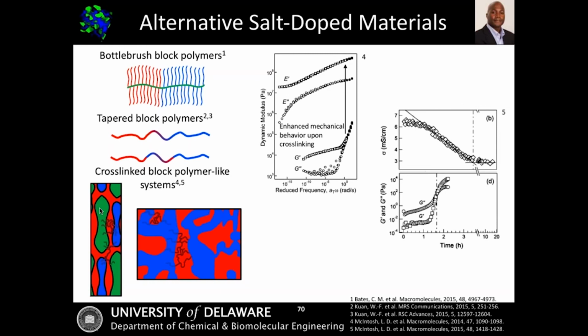But in these particular cases, they actually contain cross-linkable groups that were able to basically lock in morphologies and then allow the incorporation of both ionic liquids and/or lithium salts that could then promote conductivity without sacrificing some of the morphology. Now in this example shown here, we also see an example from the Hillmyer and Lodge groups, where basically they were using a polymerization-induced phase separation process.